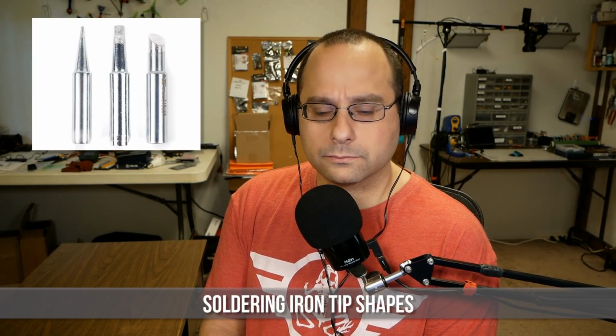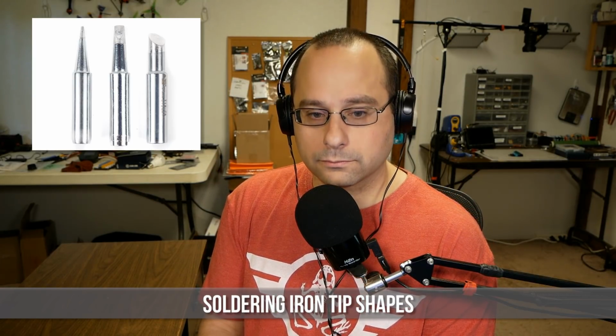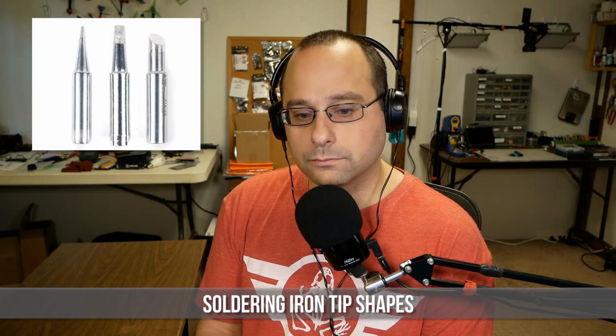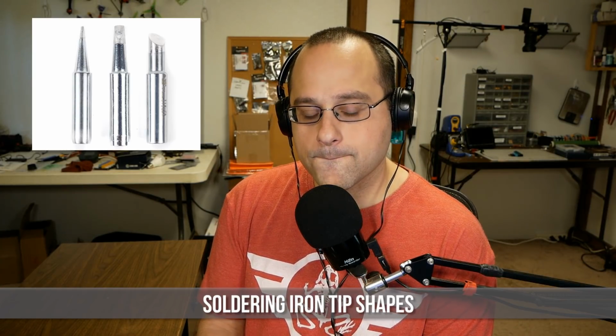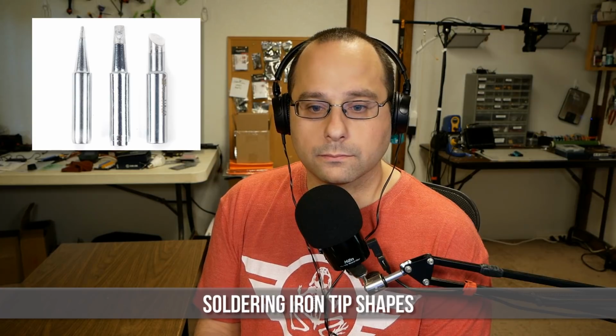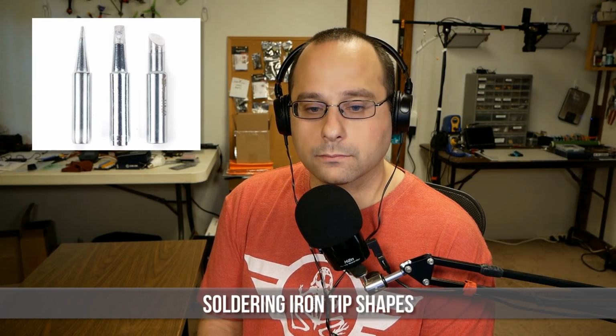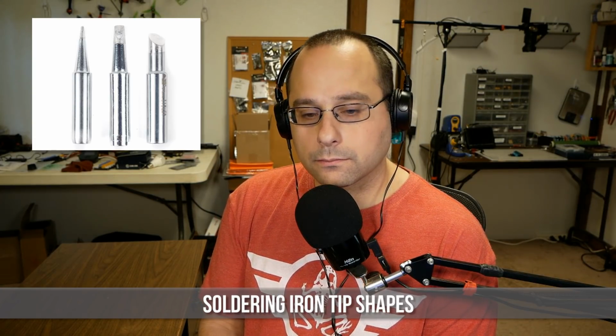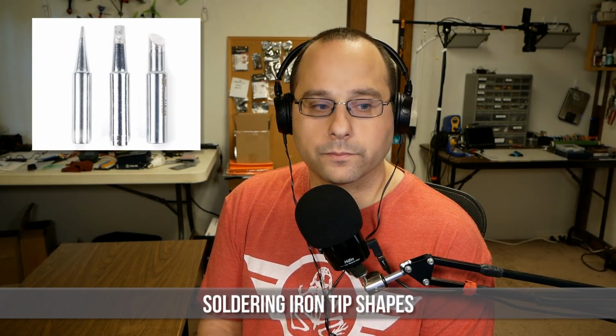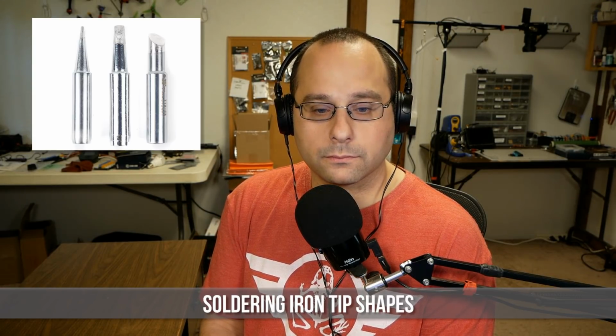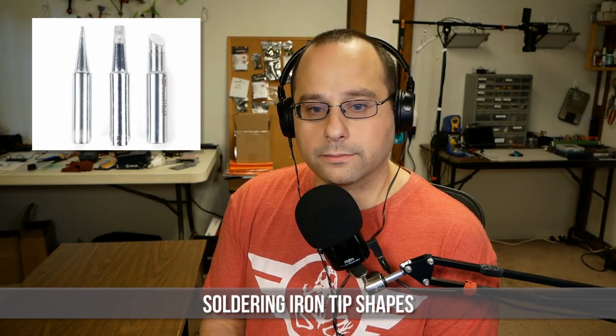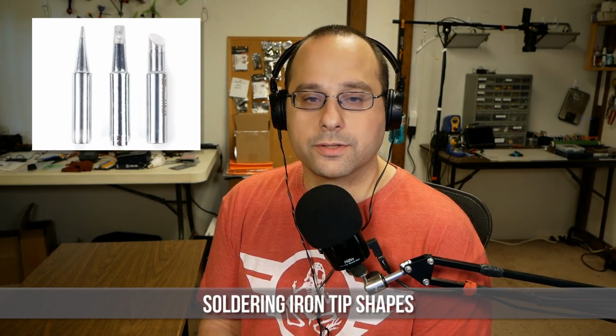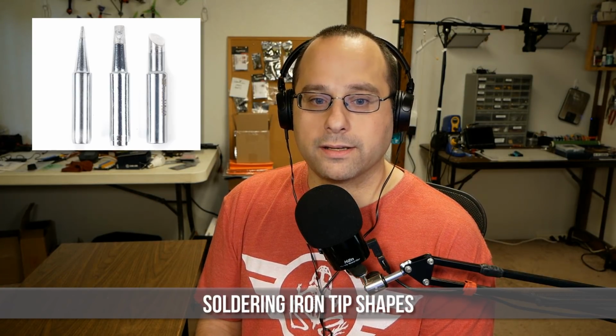It can be. It's still going to heat up slower because of the extra mass and your lower wattage on your iron. I'd recommend anywhere from a 50 to 70 watt iron. The cheaper Radio Shack irons that are usually 25 to 35 watts will have trouble with heavier wires and heavier type tips.